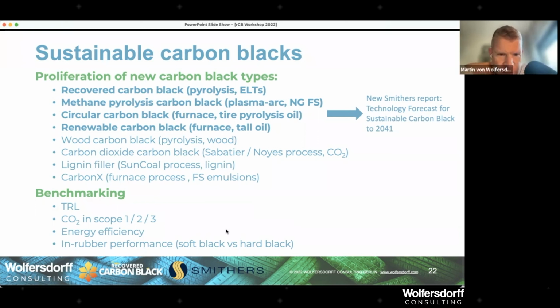Ali is asking, when referencing energy efficiency in the benchmarking, are you suggesting the efficiency of the plant producing the carbon black or something else? So remember, now we are 20 participants. I think in the start we were a little bit less, so maybe some of you only started in the middle of the webinar. At the beginning, I showed you the pyrolysis mass balance, and I said that the energy use for typical theoretical pyrolysis, 100% efficient pyrolysis, would be 356 kilowatt hour per ton of the rubber material, the tire material.